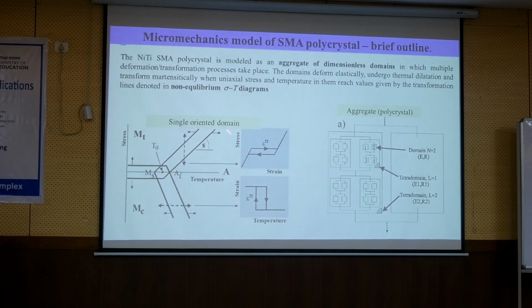I said before that for each single crystal we can make a phase diagram which shows at which stresses the transformation occurs, and then I know the transformation strain. This we measure. So we know at which temperature it occurs, and we know the strain, so we know the response of the system for a particular orientation.